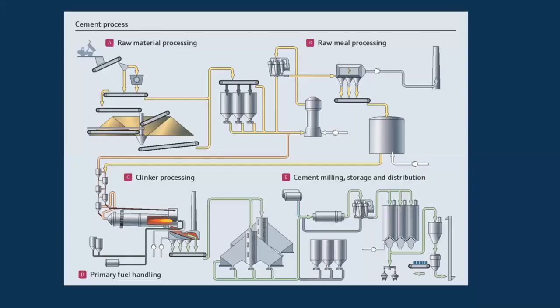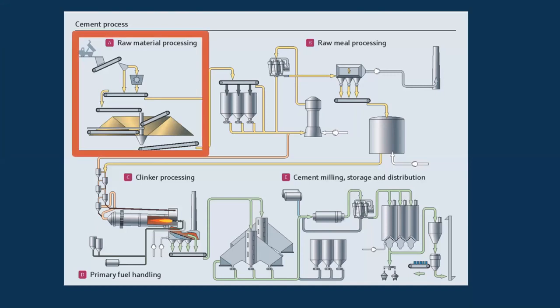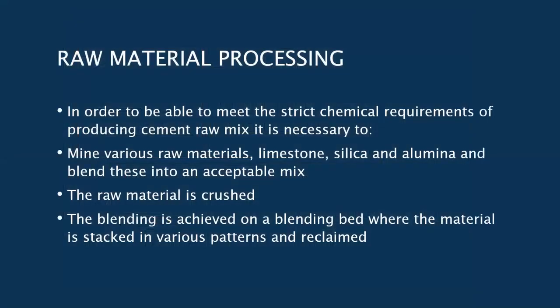The cement process we can break up into 4 basic components. The one is your raw material processing, which is the side in which I was involved. The raw meal processing, your clinker processing, and your cement milling. Starting off with the raw material. In order to meet the requirements which we've discussed, it's often necessary to mine quite a few different mining operations simultaneously. You need to mine limestone, you need to get some silica, you need to get alumina, and all this material is then crushed and blended to try and meet those requirements that we've discussed.